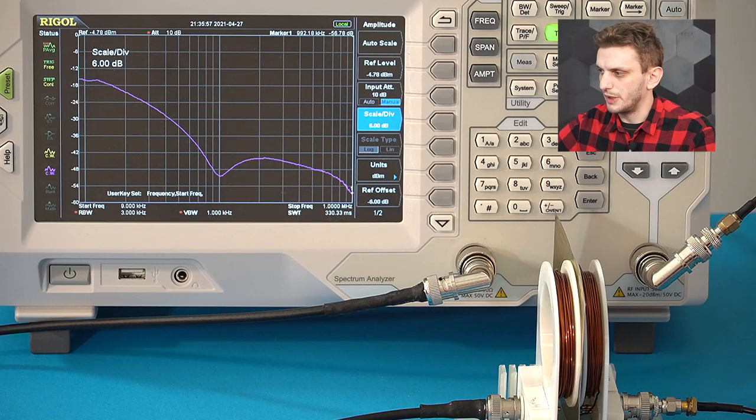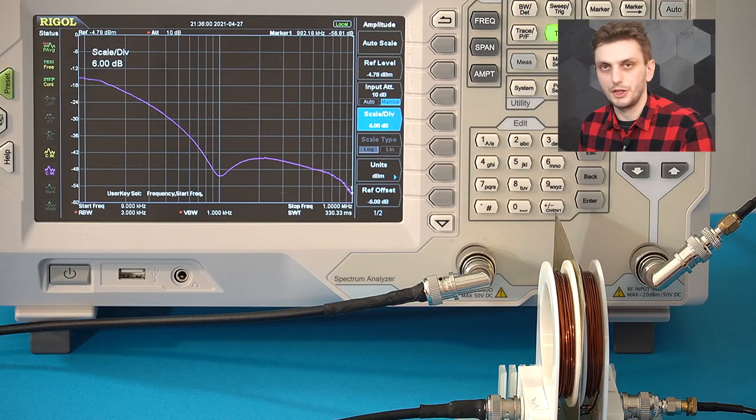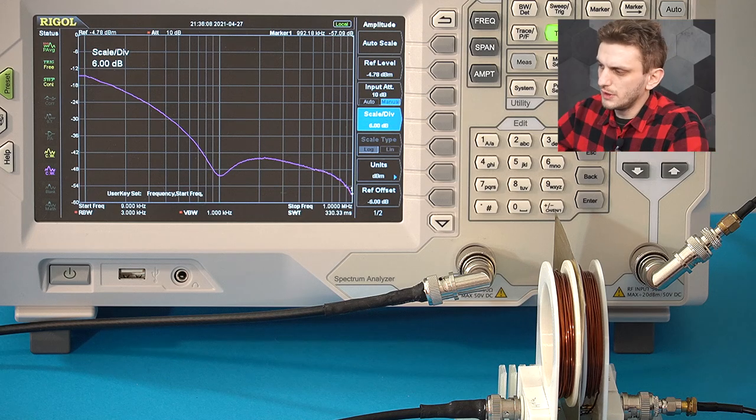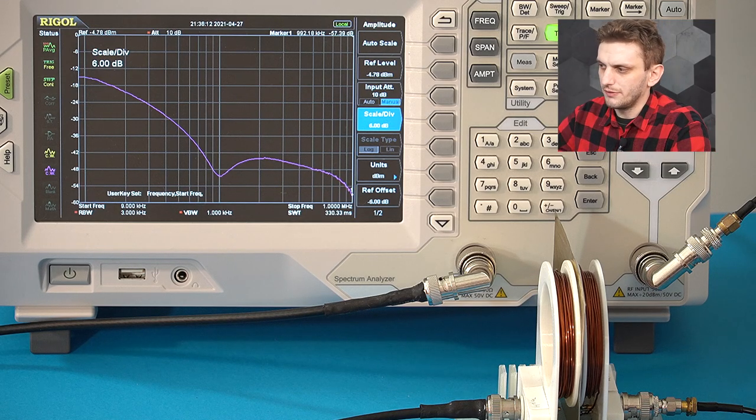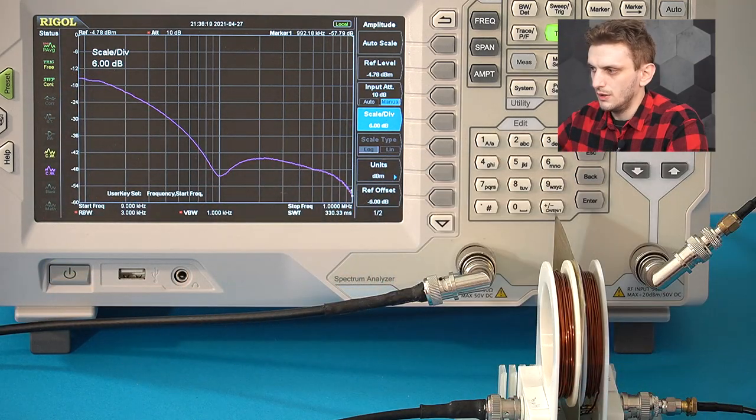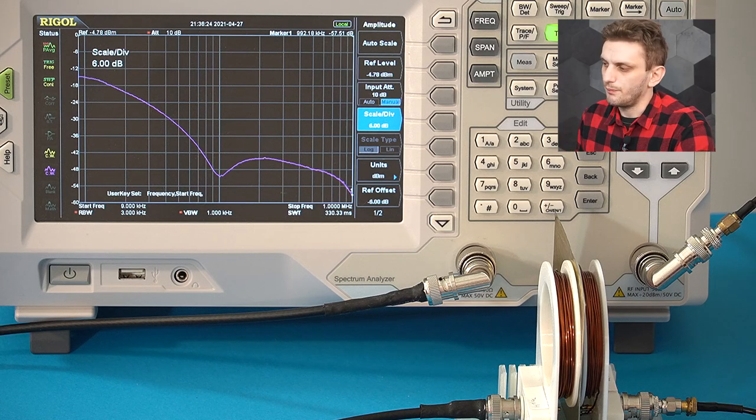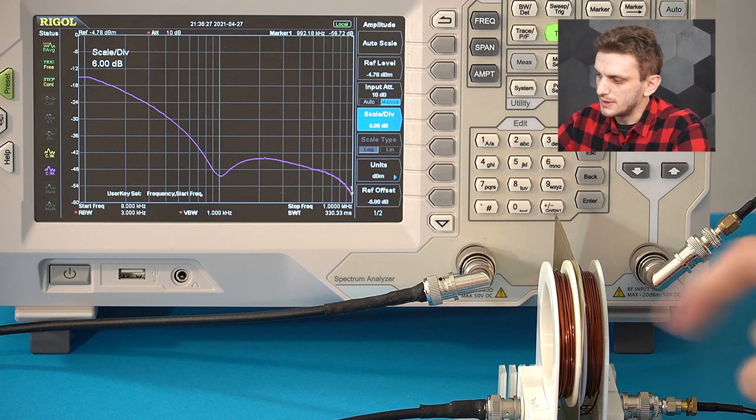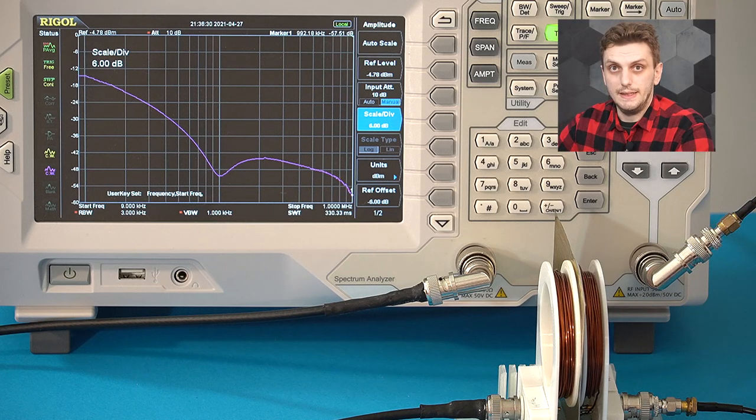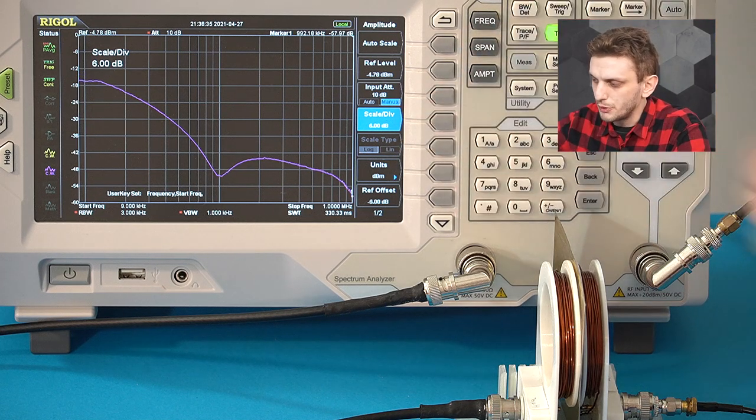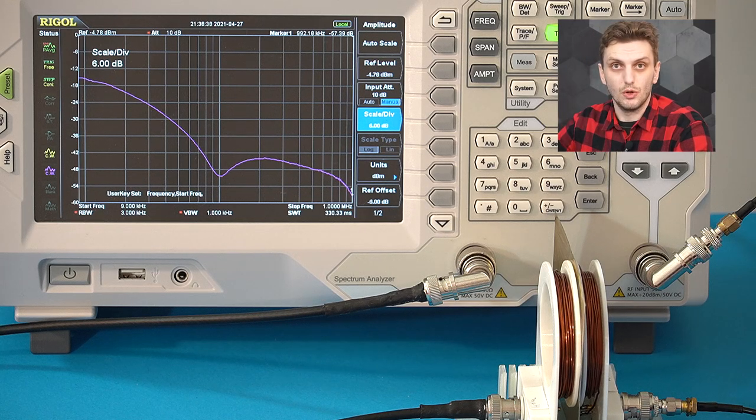If we turn to our last material, our sheet of steel, we see that we have much higher attenuation than with our copper sheet. That's because the steel is much thicker, but it's also far more permeable. But another thing that we notice is that shielding effectiveness doesn't constantly increase, it has these bumps. Shielding effectiveness does increase with frequency, but not at a constant rate. The main thing we're seeing here is that the permeability of steel is not a constant. It decreases with increasing frequency, and by the time you reach one megahertz, its permeability is almost completely gone.